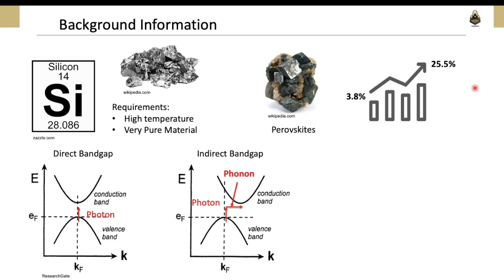Perovskites have a direct bandgap, in contrast to the indirect bandgap of silicon. To excite electrons, direct bandgap materials only require photons, while indirect bandgap materials require both a photon and a phonon at the same time, which is much rarer. Therefore, the silicon material is made much thicker to increase the probability of electron excitation. In comparison, perovskite allows 200 times less material to achieve a comparable device efficiency to silicon solar cells.